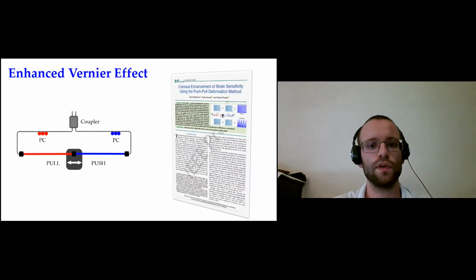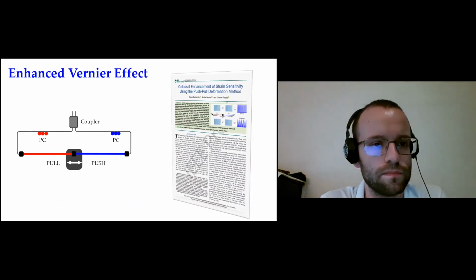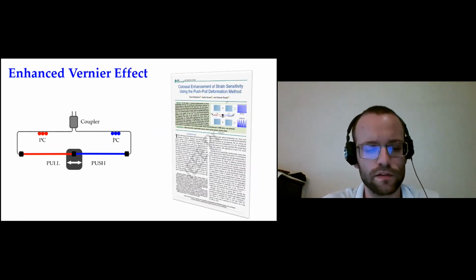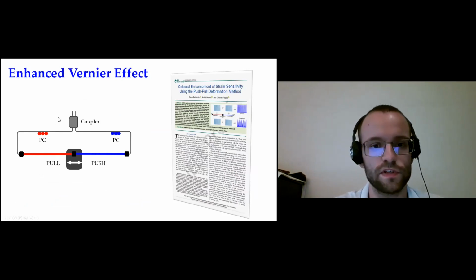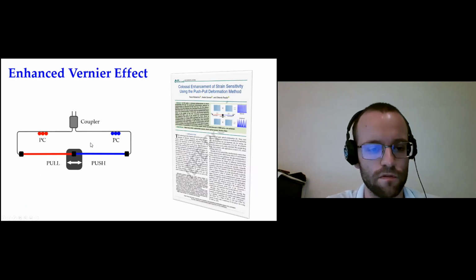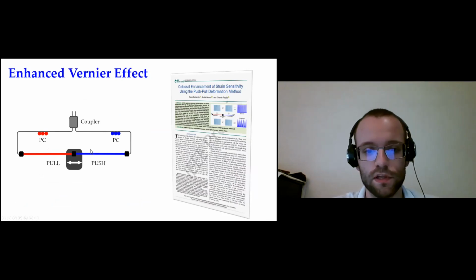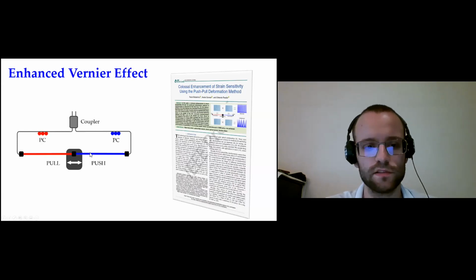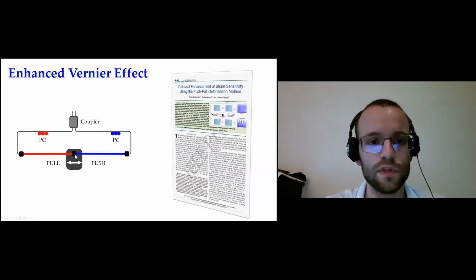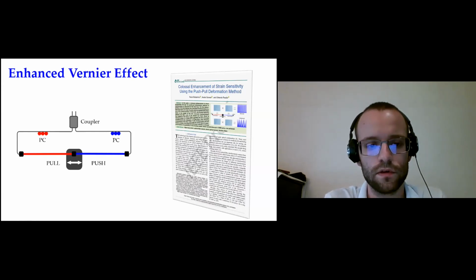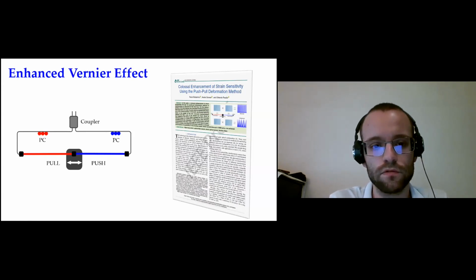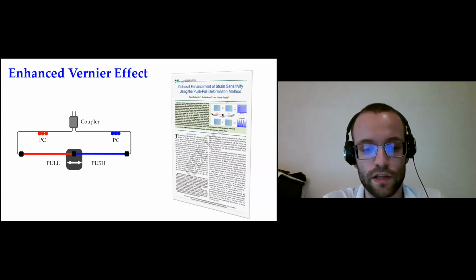After this, we start to explore the enhanced Vernier effects. In this case, we implement the enhanced Vernier effect in the strain optical fiber sensor. Typically, the strain is applied at the sensor ends, but in this case, we apply it in the middle. With this, we develop a combination between the push-pull method and the Vernier effect.